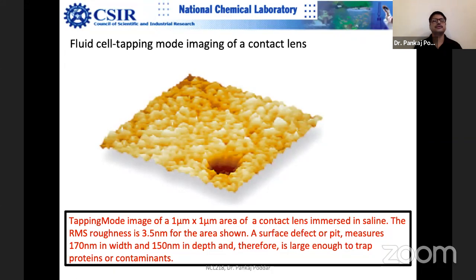And this was done in the physiological environment of the eye, which is a saline environment. So this measurement was done in the fluid cell tapping mode, keeping the environment the same. So you can see nicely how, otherwise, if you dry up this polymer, the pit dimensions will change as soon as you dry up the contact lens. So you may not be able to get the true pit dimensions when you dry it up.